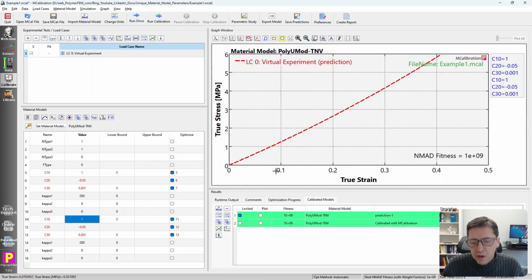And if you look carefully, the prediction is exactly the same. That is, I get exactly the same stress strain prediction with two different sets of parameters. So what I've showed here is that it really doesn't matter what the parameters are. You can get, in fact, exactly the same prediction for two different material parameter sets. And this is just a made-up example with two Yeoh hyperelastic networks.